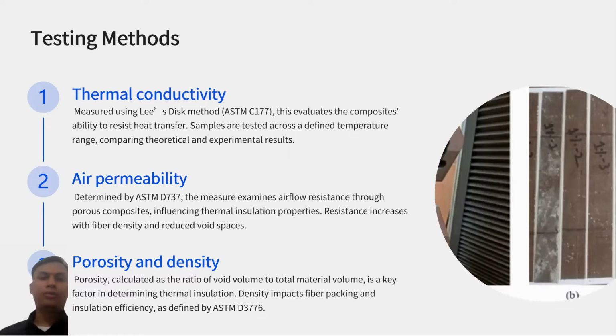After we make composites, we have to test the composite. The first, thermal conductivity testing. Measuring using this method, ASTM C177 is evaluating the composite's ability to resist heat transfers. Samples are tested across defined temperature range, comparing theoretical and experimental results.